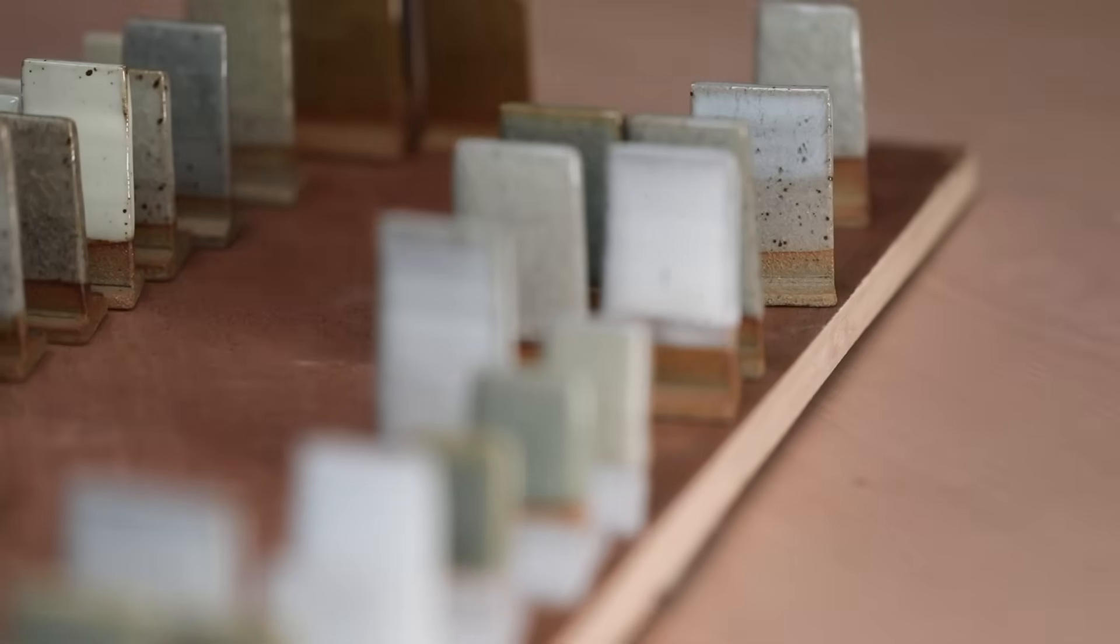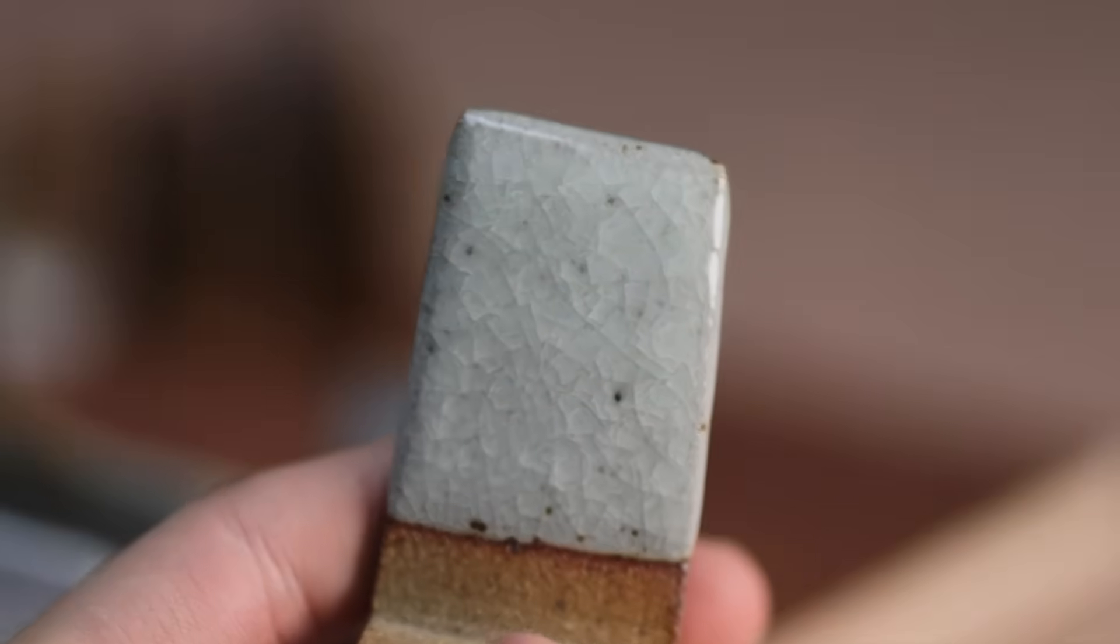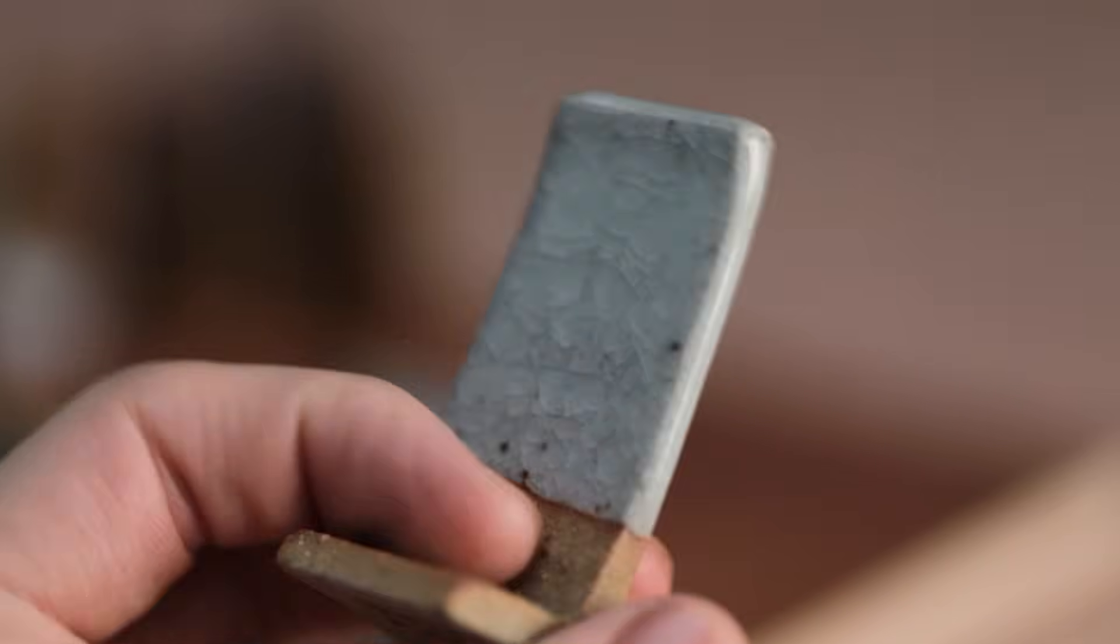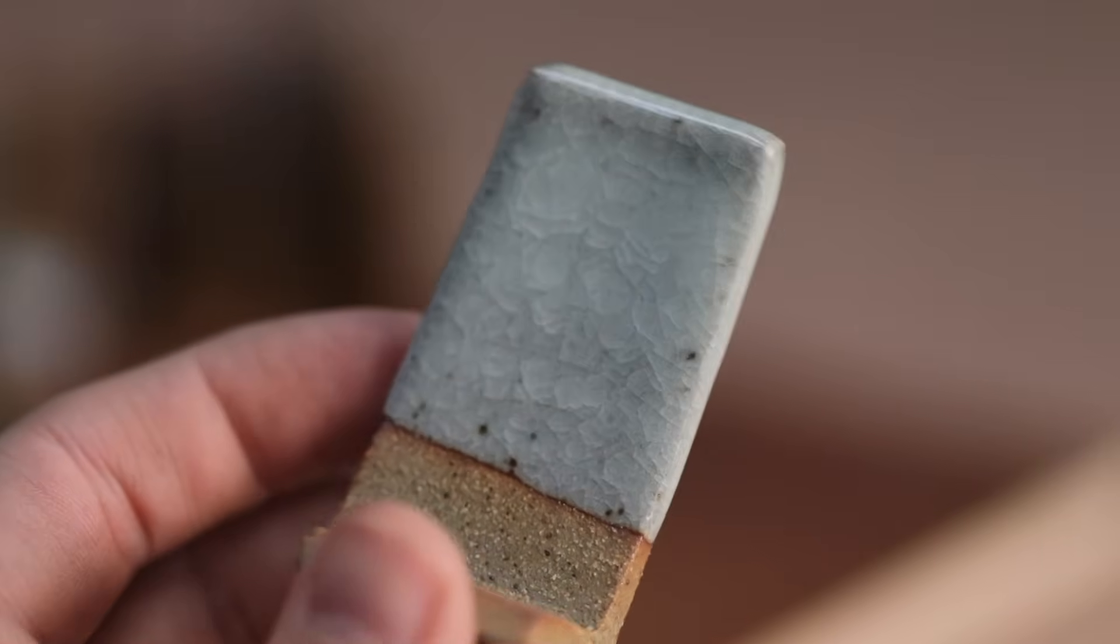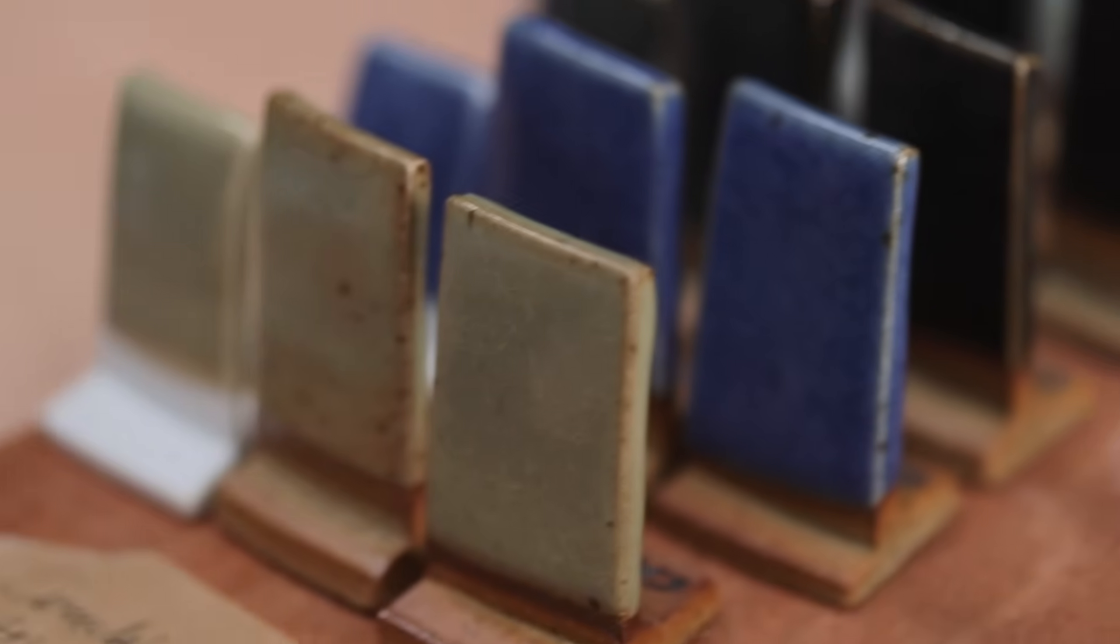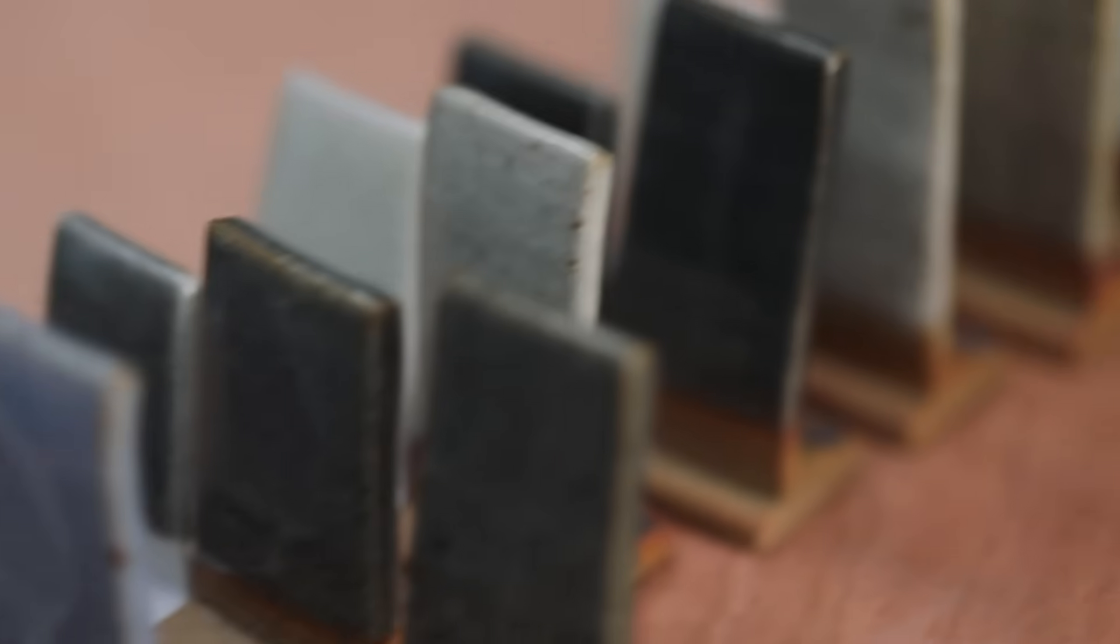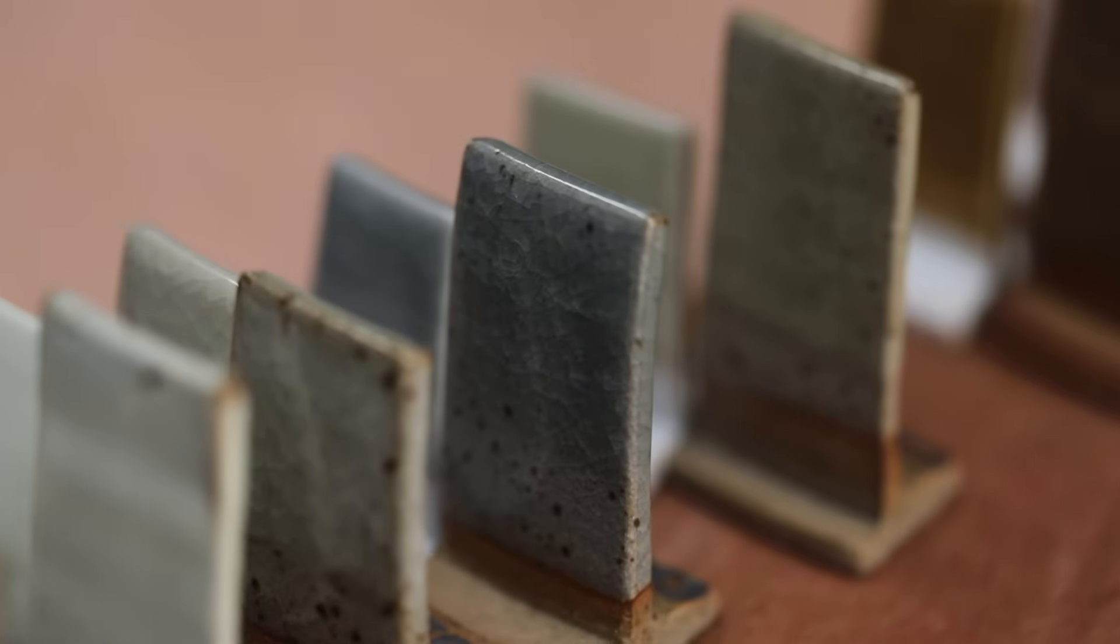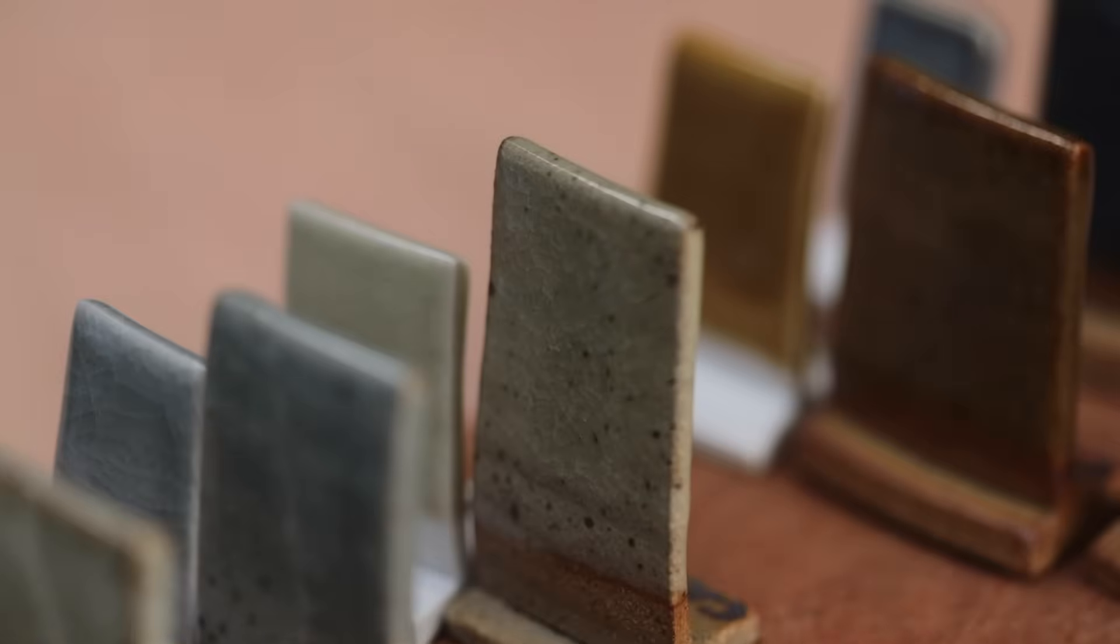I also took this opportunity to rework my current crackle glaze recipe. I upped the clay content a tiny amount, which seems to make it more stable, and I finally added bentonite to the base recipe, which means it won't settle quite so drastically in the bucket. I can't tell you how many iterations this glaze has been through, but it's a lot. So I'll begin by going over some of the crackle glaze alternatives I mixed up. Some are really lovely, but others I'll never touch again, and with these I suppose I was ultimately looking for just something else to add to my trio of colours.